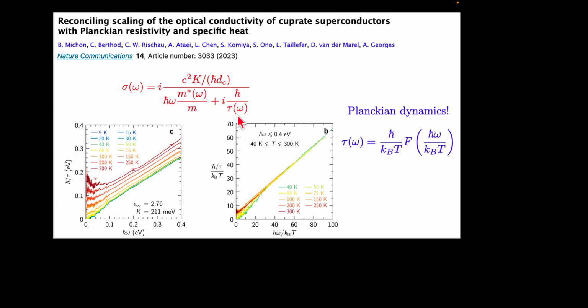And in fact, here I just focus on this 1 over tau term over here. Now, in Sommerfeld-Boltzmann theory, there's just a constant independent of frequency. But generically, without making any assumptions on the microscopic physics, you can write it in this form where tau is frequency dependent. So what they find when they measure tau is that it's strongly frequency and temperature dependent in a way that you can't get from a liquid theory. And in particular, it seems to obey this remarkable form. It's just exactly this Planckian time times some function of frequency over temperature. And that's what this is showing you. At high frequency, this tau of omega is linear in omega. But 1 over tau is of order 1 over omega, sorry. That's this plot here.